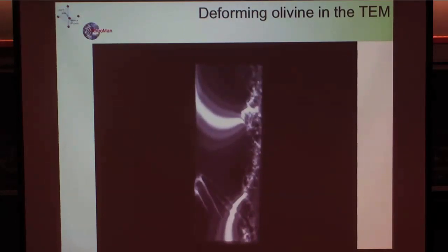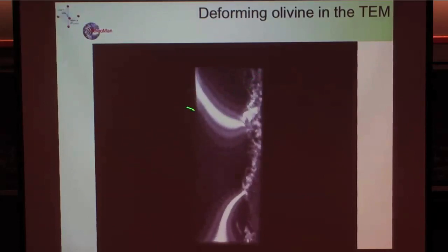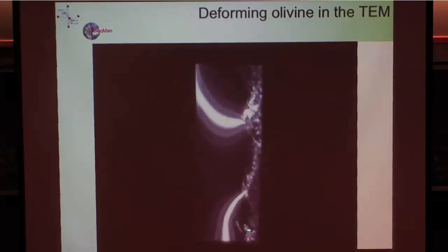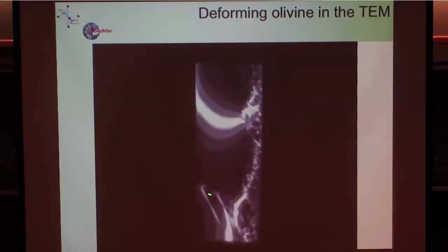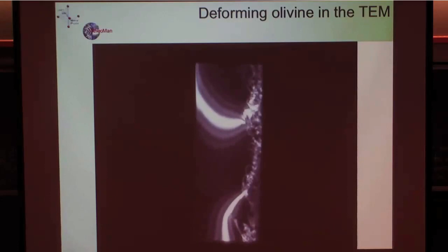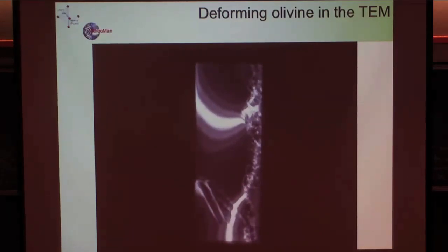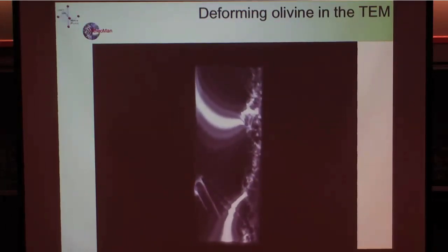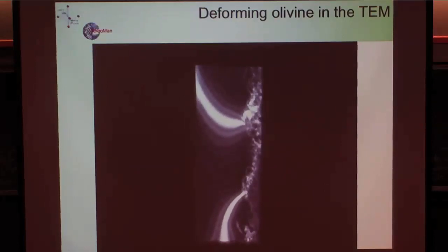We apply the colors. It's just the diffraction contrast, so you forget about that. You just have to focus. This is because the specimen is a little bit bent, so you have broad contours, but you just have to concentrate on the loops. These are the dislocations which are here, otherwise it's black and white. No, it's room temperature. We cannot heat so far. We apply here like 300 micronewtons, which is 1.1 GPa, you know, force over area.